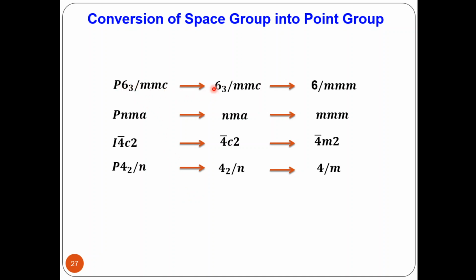In the first step, you should remove the P, and we have noted that the type of the unit cell is primitive, so we are left with 6_3/mmc, and then we have considered 6, and then the rest of the symbols are similar. This is 6/mmm. P nma, nma with no P, and then mmm, because this is a glide symmetry, and again a glide symmetry, and are replaced with m. Similarly, these and these, hopefully you have got them.